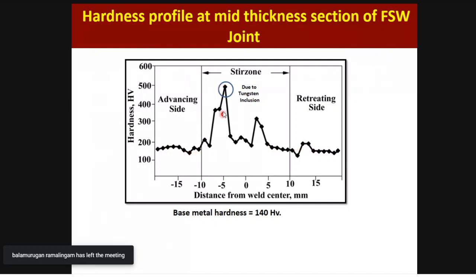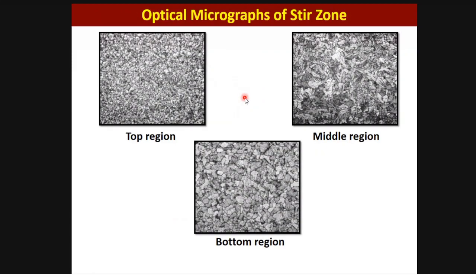So this is the peak. It's going through, the very high hardness was recorded in the stir zone. And we went for the microstructure analysis. You see that in the top region, microstructure and bottom region and middle region, there is enormous change.